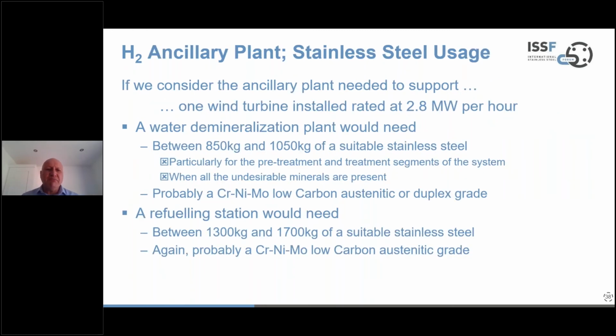Now, if we start to try and put that into context, what does it mean in terms of volume? If we consider a modular wind turbine hydrogen production system rated at 2.8 megawatts per hour, then for water demineralization you would need around a ton of stainless steel. There's a bit of flexibility based on design, but it's something close to a ton of stainless steel. That's in the pre-treatment and treatment segments of the system, where the water is still full of undesirable salts and minerals.